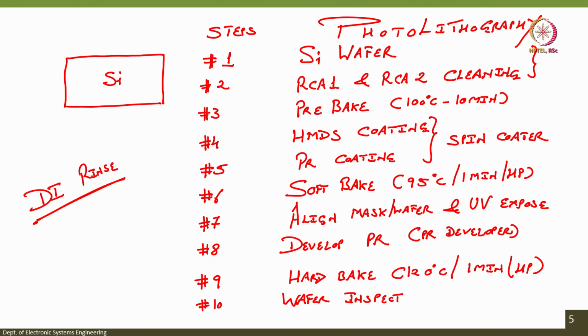Step number 1 is you get a silicon wafer, then you perform RCA1 and RCA2 cleaning. Then the next step is to pre-bake. Pre-bake is to remove any moisture from the wafer. Next step is HMDS coating, used to improve the adhesion of the photoresist onto the silicon wafer. The next step is photoresist coating. Both HMDS coating and photoresist coating are done using a system called spin coater. Next step is soft bake. The wafer coated with photoresist is baked on the hot plate for 1 minute at 95 degrees centigrade.